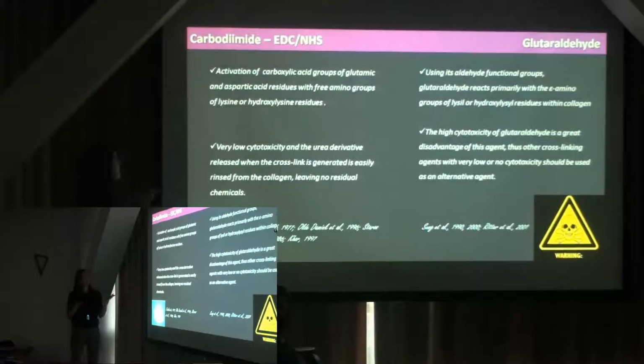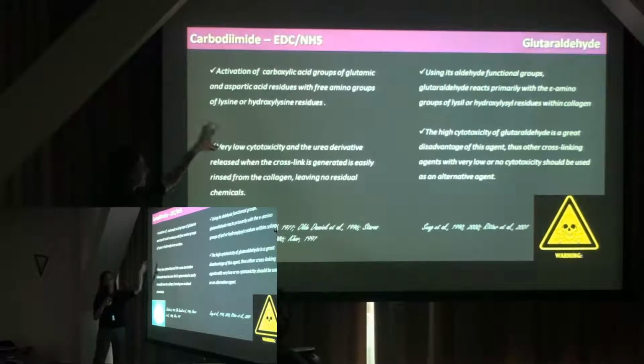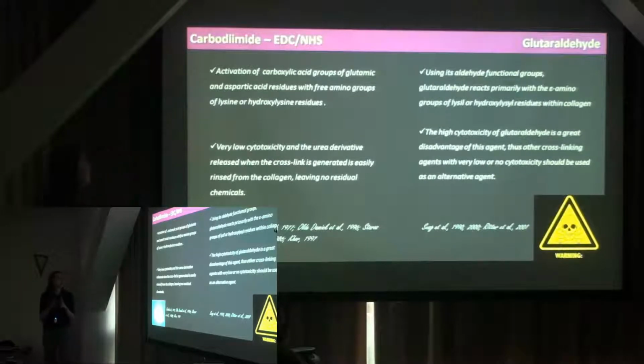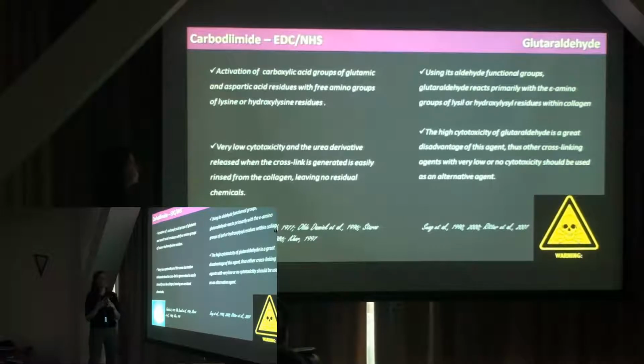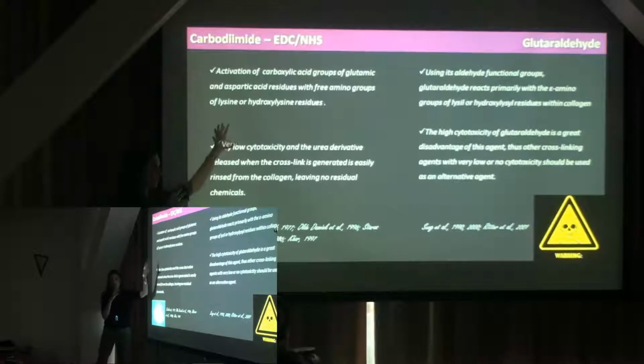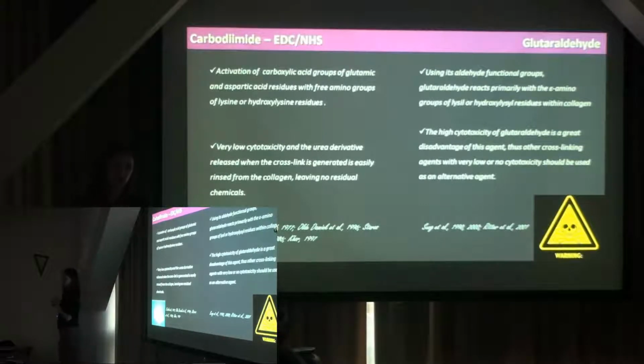All right, so we have also explored synthetic crosslinkers, carbodiimide. I guess people in biochemistry labs use it a lot in the processing of samples. Basically, the mechanism of cross-linking collagen is well known. It's not as powerful as the proanthocyanidins, but it's very stable over time. Wherever there's a cross-link, it doesn't really change. These are covalent bonds that are introduced. The drawback is that molecules or fibrils have to be very close to each other, otherwise it can't make that link. It basically initiates the process, but it doesn't participate in the final chemistry.